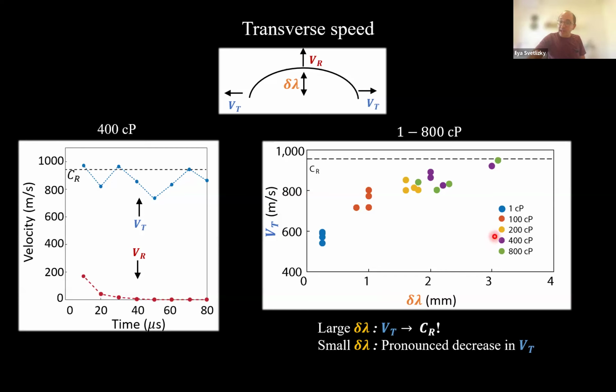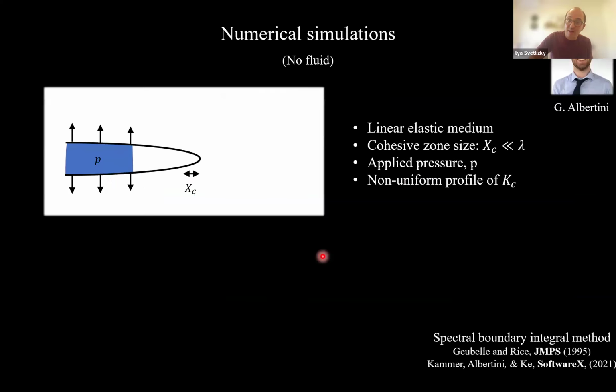And what you get is that for large jumps, the transverse velocity approaches the Rayleigh wave speed, whereas as the jump size decreases, you can reach almost half of the Rayleigh wave speed. So we were very curious about this result for some time. We put some amount of effort to try to come up with a model to explain how cracks expand in a transverse direction. We are not aware of anything like that in the literature, and pretty much when we gave up, we went begging for help to Gabriele.